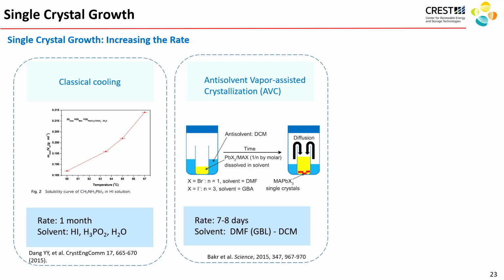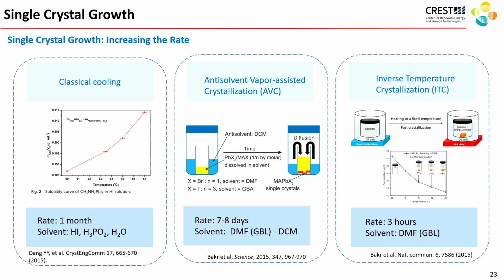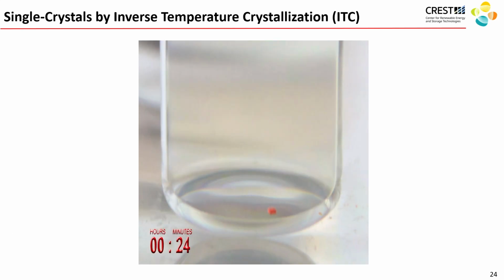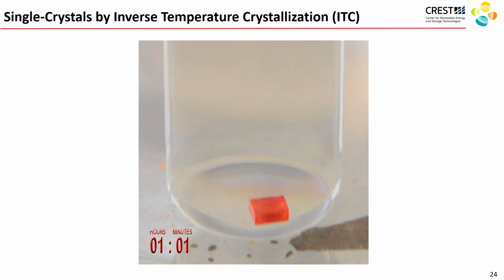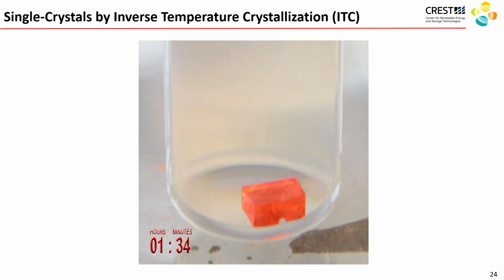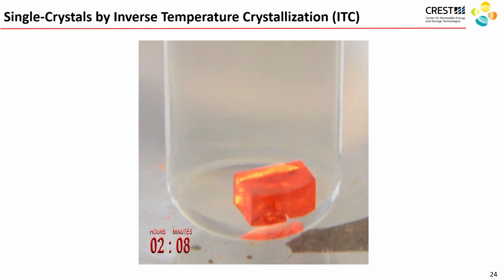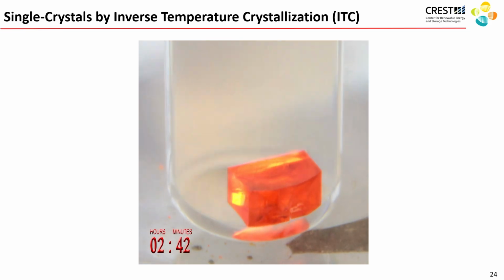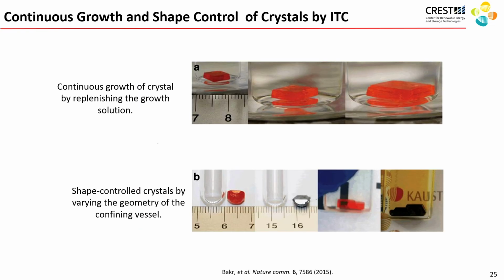So typical ways of growing crystals, either through cooling or through anti-solvent methods, require weeks to do. What we've done is we've discovered a method that allows us to grow the crystals within hours. For a crystal that normally would take a week to grow, basically we found a way of initiating supersaturation in the solvent through a method called inverse temperature crystallization. This allows the crystals to grow at a very rapid rate, and allows us as well to control the shape of the crystal.